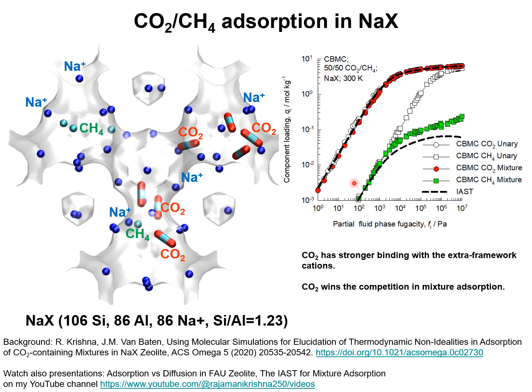We see that in the mixture, the CO2 loadings are practically the same as for the pure component. Whereas for methane, the loadings are considerably lower by about 1.5 orders of magnitude than the corresponding pure component values. In other words, in the competition for mixture adsorption, CO2 wins the battle hands down and methane loses this competition.